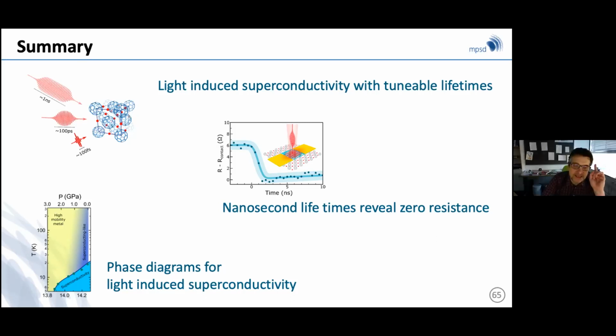Just 1 second, Alex. What you just said, let me defend it. Sigma 1 and sigma 2 come out of the data just by measuring amplitude and phase. So small r, r1 plus i r2. And there you extract sigma 1 and sigma 2 with no bias. When we extract sigma 0, there we fit it with a Drude-Lorentz fit, for lack of a better. But this is only every time we try to say, what do we expect the equivalent zero frequency conductivity to be?